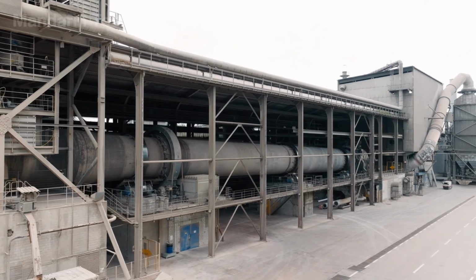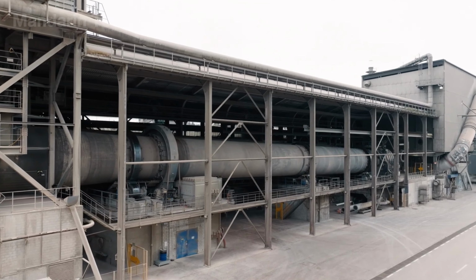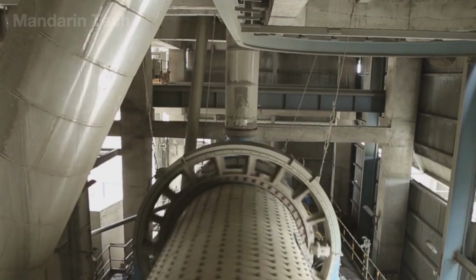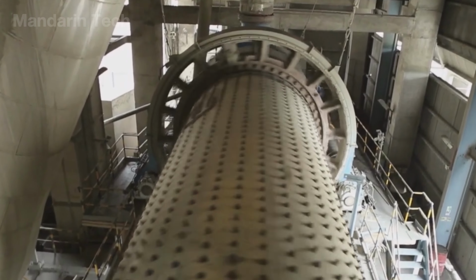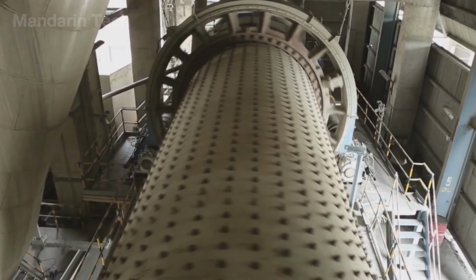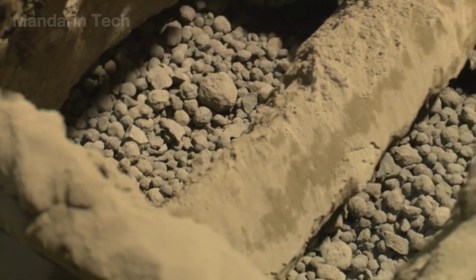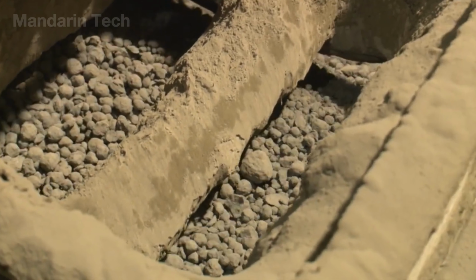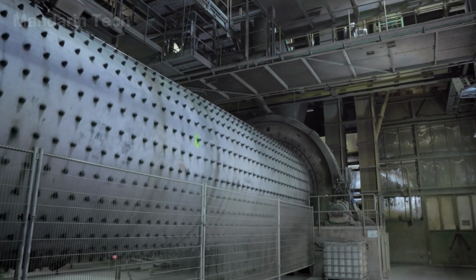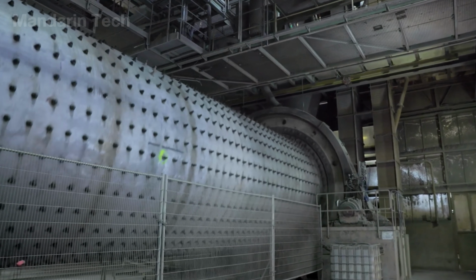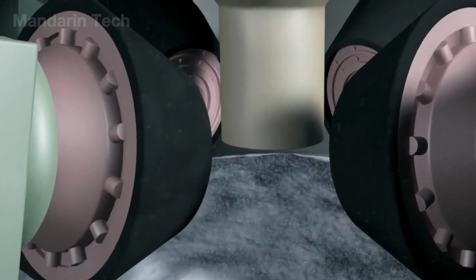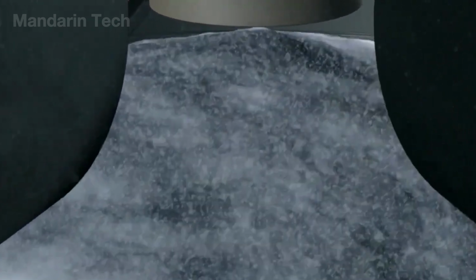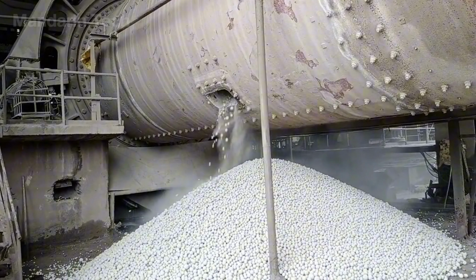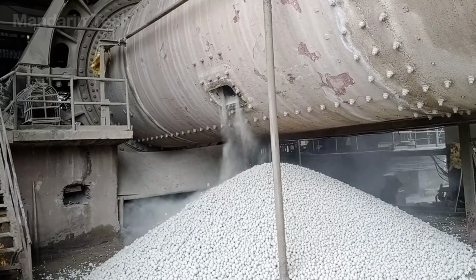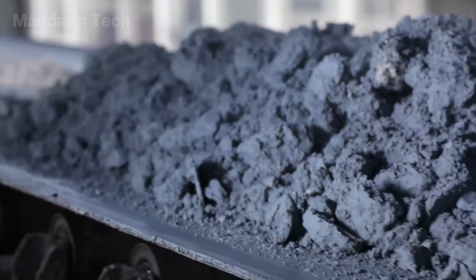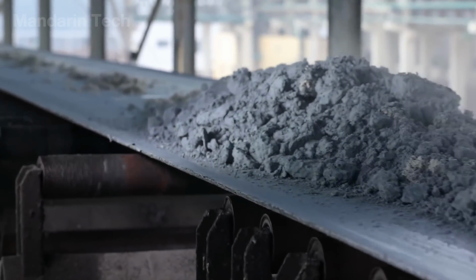The residual heat from the cooling process still clings to each clinker as they slide into the high-capacity grinding mill, processing several hundred tons per day. Here, the clinker mixes with about 3 to 5% gypsum and mineral additives, such as fly ash or ground granulated blast furnace slag. Under continuous pressure and friction from steel balls or rotating rollers, the mixture gradually breaks down into fine cement powder with a fineness of around 4,500 cm²/g.